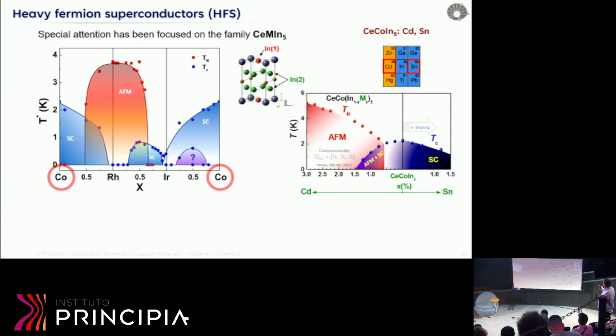So if you introduce electrons by introducing tin in this matrix, electron doping just suppresses T_N monotonically. However, when we introduce holes in this matrix, we can tune the system to the left side of this phase diagram, and we can reach magnetism, antiferromagnetism over there. And by that time, with quantum criticality in evidence, all of this was a very good scenario for us to investigate the coexistence and how this magnetism was emerging over there.